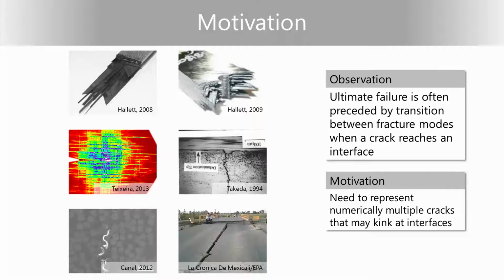One thing which is very specific about composite structures is that if you want to design a composite structure until its breaking point, you have to be able to simulate not just the formation of the first cracks, but actually the formation and growth of many cracks that grow, they meet each other, they interact, they change direction, which we call kink, they kink into another direction, and it's only subsequently, after all these interactions happened, that you get the final failure of your components. And therefore, that poses an enormous challenge for simulation tools. So this is what we are trying to address with this.